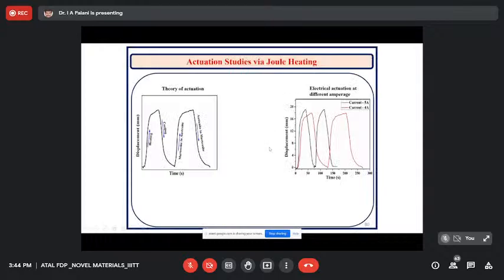Okay, so the idea we got from this is that we could directly fabricate shape memory alloy structures using the friction stir welding process. And the most important thing is, since we could directly weld a defect-free structure, we could study the actuation characteristics in a much better way.